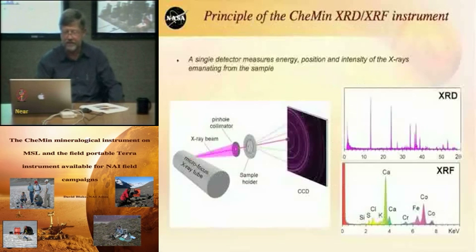So now I'll give you a brief insight into how it works. Cobalt X-ray tube, microfocus tube. A beam starts here at about 50 microns diameter. There's a pinhole collimator which produces a collimated approximately 50 micron source. It goes through two thin plastic films which contain the sample between them. The sample consists of 150 microns and below crushed powders, and this whole thing is shaken so that the powder flows like a liquid inside this cell, so that over a period of time all the grains pass through this tiny beam in random orientations.